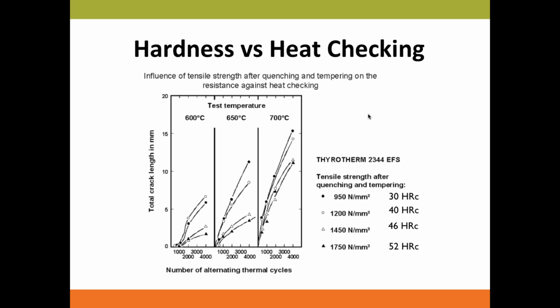So what do these two different hardnesses mean to the end user? On this chart, you can see if we put this H13 material and subject it to three different temperature cycles, 600, 650, 700 degrees Celsius. At the bottom, it shows you the thermal cycle or temperature cycle it goes through.